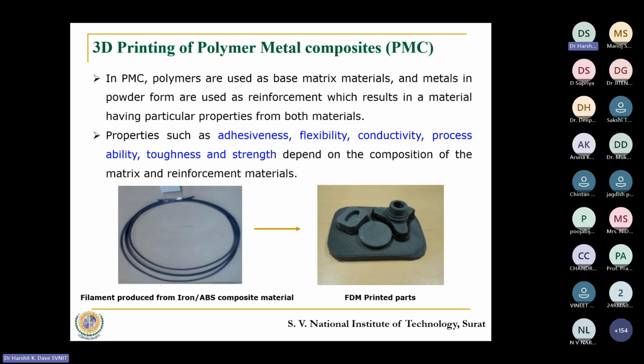When we are mixing these two materials, our intention is that we need to focus on properties like adhesiveness, flexibility, conductivity, processability, toughness and strength. All these properties sometimes are good in a polymer and sometimes they are better in metal. So the proportion of mixing metal into the polymer filament would be tricky. Suppose I want to try with, say, copper metal particles mixed into, say, PLA filament. Then if I choose a filament which is 30% copper or which has 3% copper, both of them would create a part which would exhibit totally different levels of properties. So the selection of the proportion for a certain application becomes very important.